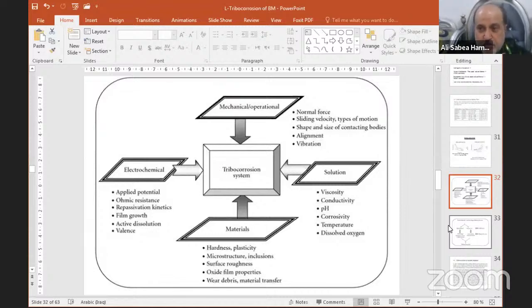Because of depassivation, stainless steel 316L may be subjected to an aggressive environment. The body fluid is an aggressive environment. It leads to removal of the passive film, Cr2O3, at the surface. Depassivation leads to fretting corrosion or tribocorrosion of 316L stainless steel, and it can also affect titanium 6 aluminum 4 vanadium or titanium 6 aluminum 7 niobium, leading to fretting corrosion.